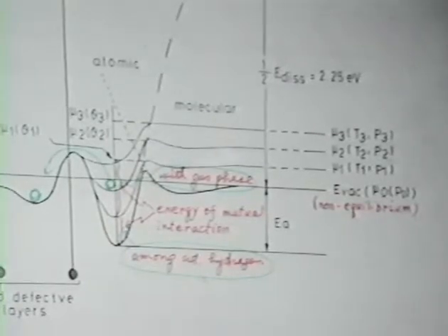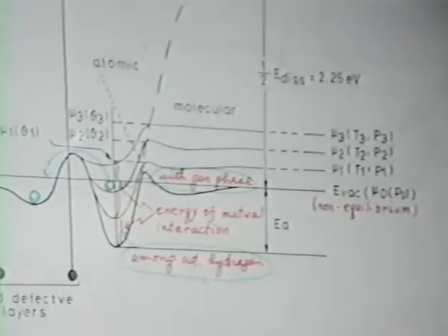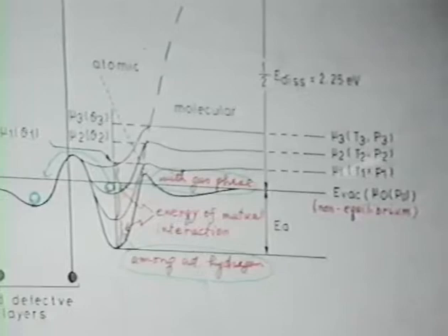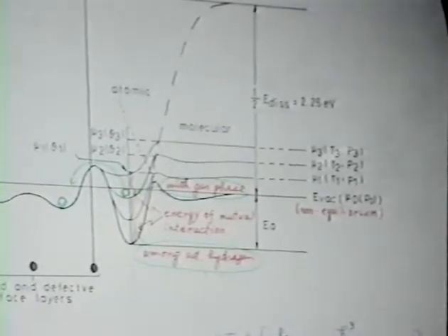So we have a well-known potential curve here, but with increasing the temperature and the pressure of the gas phase, we have an increase in the chemical potential, which is in equilibrium with the chemisorbed state, so that the chemisorbed state becomes very unstable. With some pressure and temperature, the adsorbed state might be transferred to the subsurface side, if the iron metal has some capability to accept the subsurface hydrogen. This is the second problem.